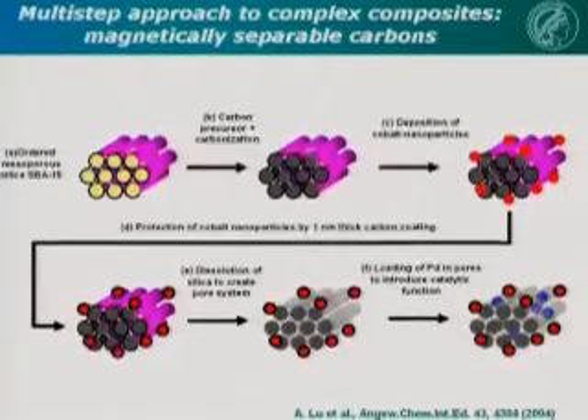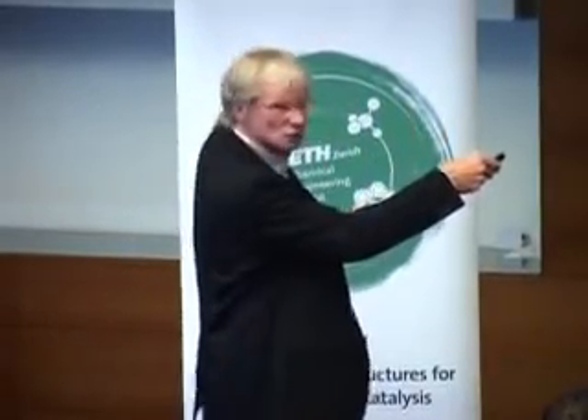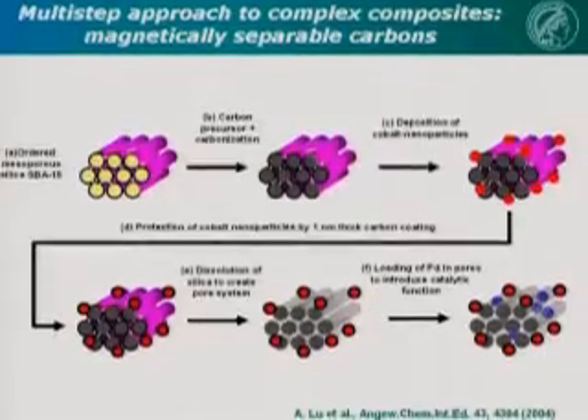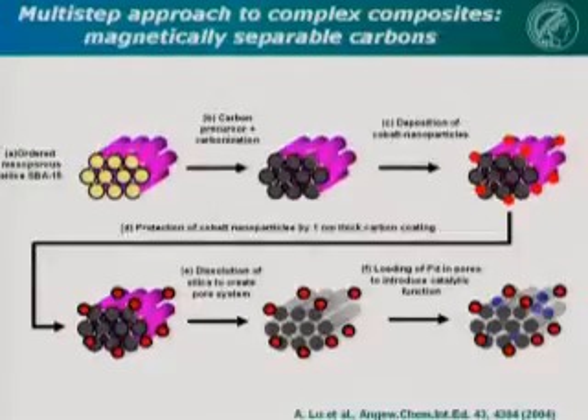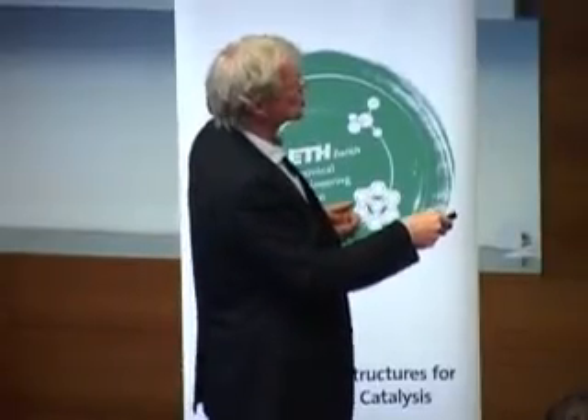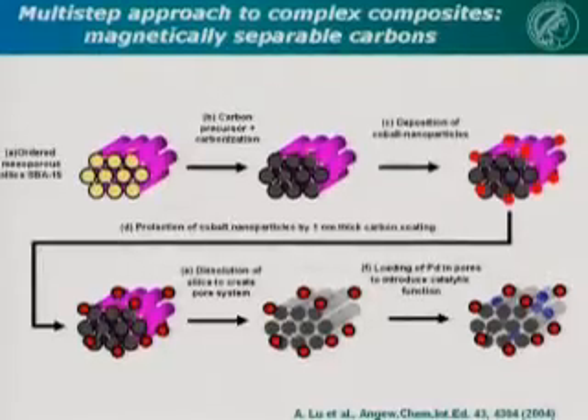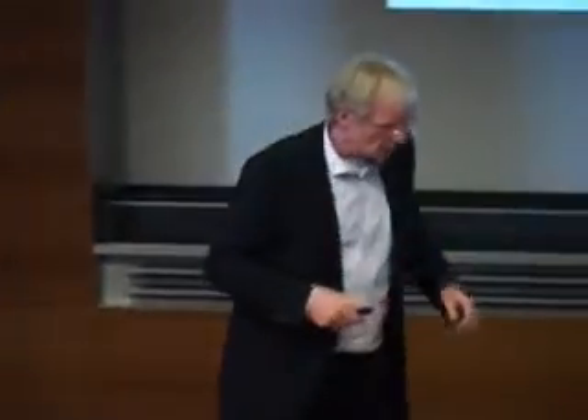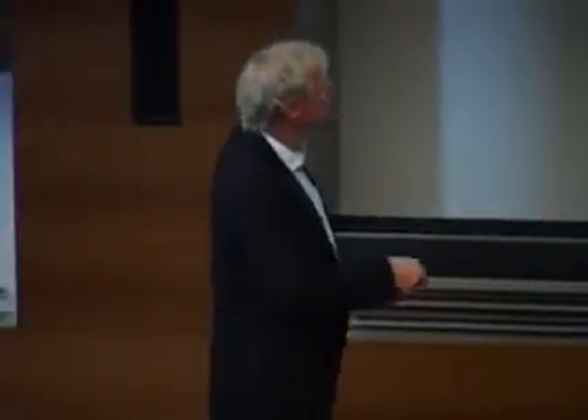This is something Anhui Lu did almost 10 years ago, again starting from these ordered mesoporous materials, where he placed a carbon precursor inside, so that he could only externally functionalize this material, because we wanted the pore system for something else. We wanted to place the catalyst there, and the magnetism should sit on the outside. So he protected the pores here, placed cobalt particles, 9 nanometer, on the outside, which couldn't go inside because that was protected. He coated them with carbon, because cobalt otherwise would corrode, and leached the silica, and then we had the carbon pore system here, in which we could fill catalytically active materials. And you see, it's nicely magnetic.